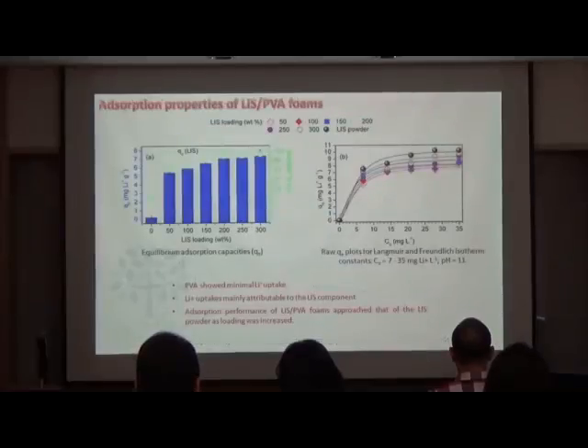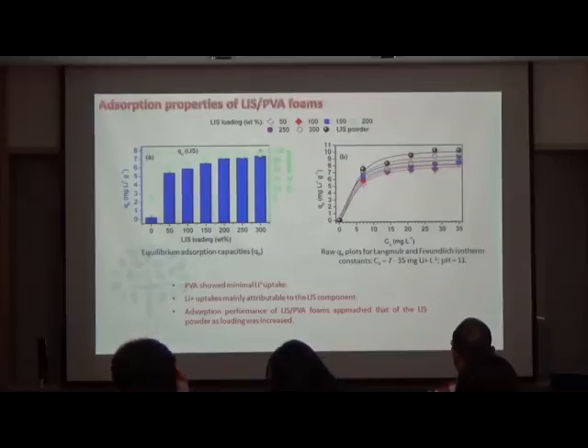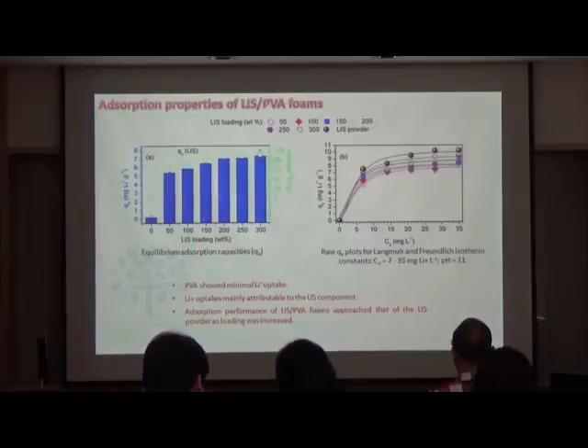Now, the equilibrium adsorption results of the composite foams with different adsorbent loadings demonstrate the effect of PVA on the adsorption capacity of the LIS. At an initial concentration of 7 ppm, the LIS powder has a lithium uptake of 7.8 mg per gram, while the pure PVA foam has a minimal uptake of 0.1 mg per gram, which suggests that most of the lithium adsorption is caused by the LIS component. Furthermore, the adsorption isotherm of composites with varied loadings at varied initial concentrations consistently showed the same trend as this figure, which indicates that as the LIS loading is increased, the lithium uptake approaches that of the LIS powder.